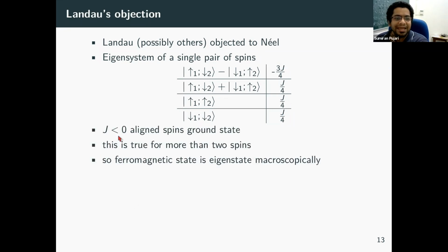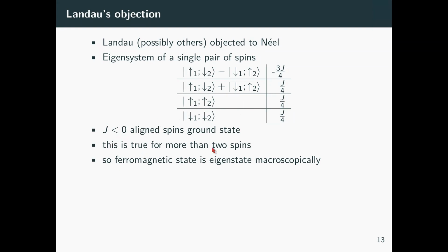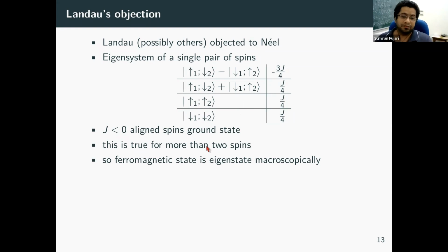Now depending on the sign, say J is negative, then it turns out this triplet subspace, for example up-up, becomes the lower energy subspace. That's the ground state subspace. And it turns out this basic argument is also true for more than 2 spins. So if you have 5 spins, 5 of them point up, that would be the ground state, and so on. If you have 100 spins, they will all point up or down. And so the ferromagnetic state actually is an eigenstate of the ferromagnetic Heisenberg Hamiltonian.